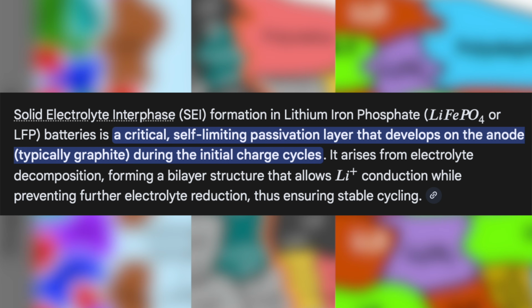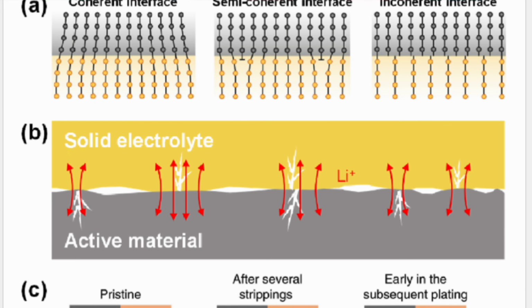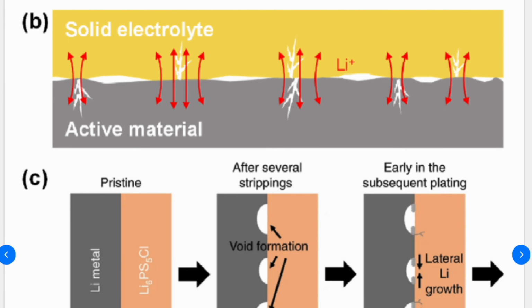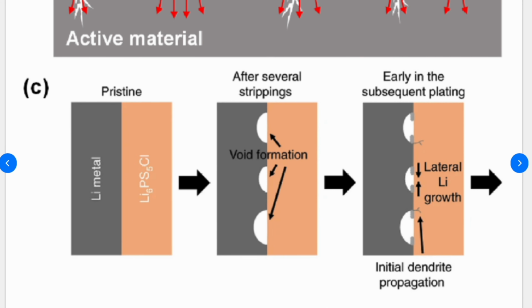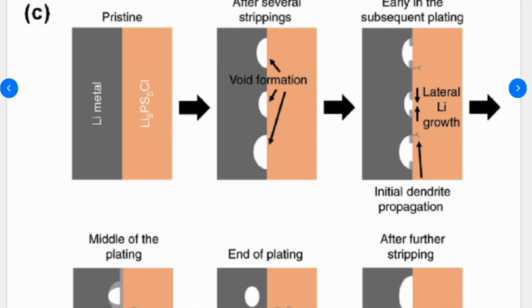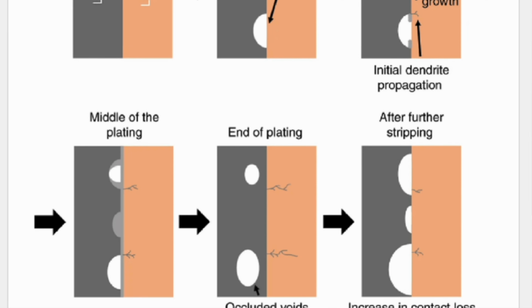Then there's interfacial chemical instability. You see, when a liquid electrolyte-based battery charges for the first time, an SEI forms, or a solid electrolyte interphase, and part of the battery capacity is lost right there. SEI formation is largely a one-time front-loaded process, and this layer is necessary for the battery to work. But with a solid-state battery, layers of this type can form over time as solid electrolytes can react with the electrodes themselves. These layers can reduce conductivity, grow brittle, and create fragility within the battery, as well as reduce the life of the battery over time. And the layers often continue growing during additional cycling.